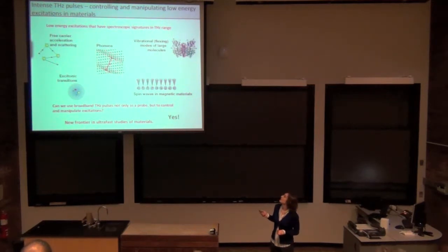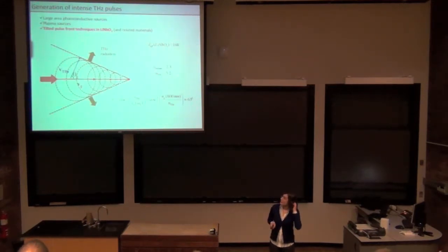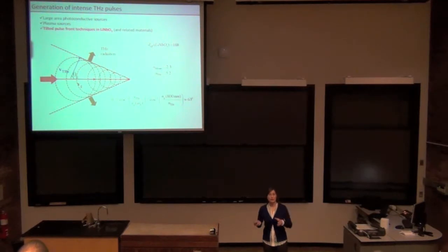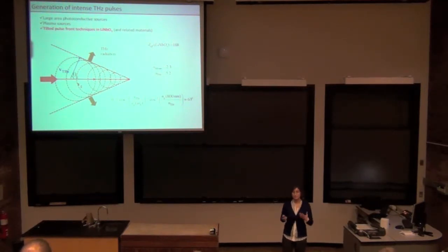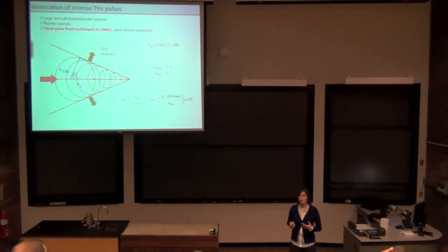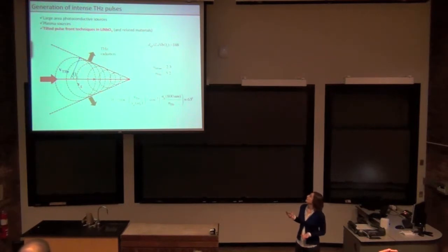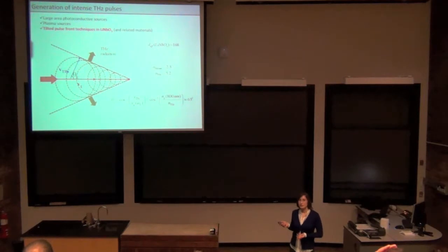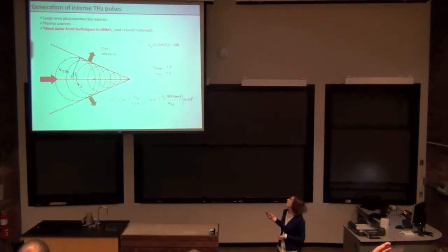How do we generate those pulses? Well, as I told you earlier, we rely on nonlinear effects in semiconductors to generate terahertz pulses by optical rectification. For that process to be efficient, you need a high nonlinear coefficient. The inorganic material with probably the highest nonlinearity is lithium niobate, which is excellent. It's almost 3 times as high as zinc telluride, so it would be a wonderful material. Except there is a problem, right?